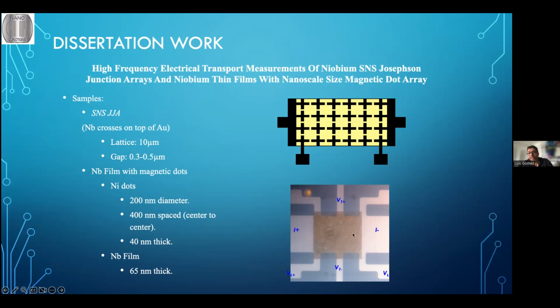So my system here was basically a niobium island deposited on a gold film. And the other system that I studied in my PhD thesis was a film of niobium, represented by the clear path here, deposited on top of a square array of circular nickel dots. You cannot see the dots here, but there was an array of nickel dots of the same diameter, separated by a distance. The diameter of each dot was 200 nanometers, and they were about 40 nanometers thick. They were distributed on a square array, and from center to center, each one of those coins, if you want to call them that, because they're quite thin, they were separated by 400 nanometers. So there was a gap of 200 nanometers from the edge of each dot in all directions.